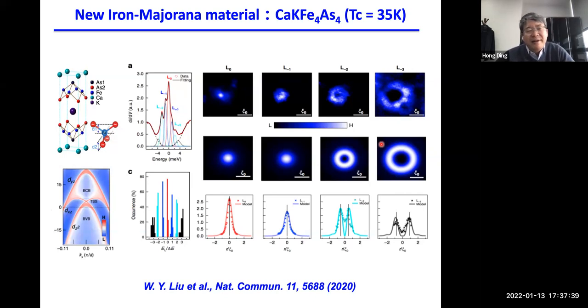In this material, the band inversion is actually induced by symmetry breaking. This is a double layer. It breaks the glide mirror symmetry, which induces the band inversion at the gamma point. This is very interesting, and we think it may have some other fascinating properties, as we are right now trying to understand some exotic behavior in this material.